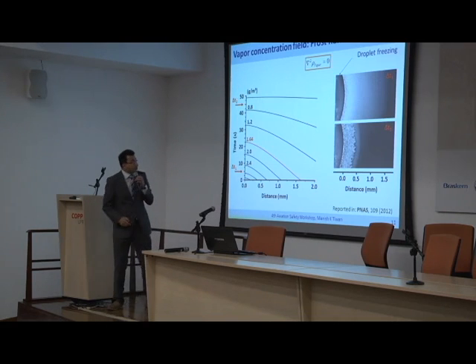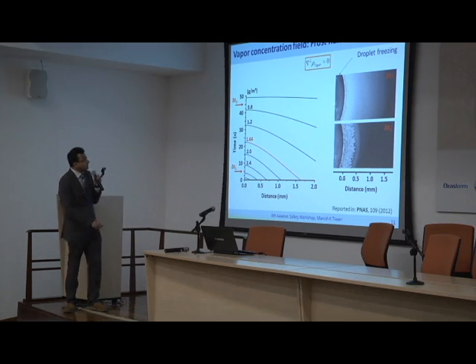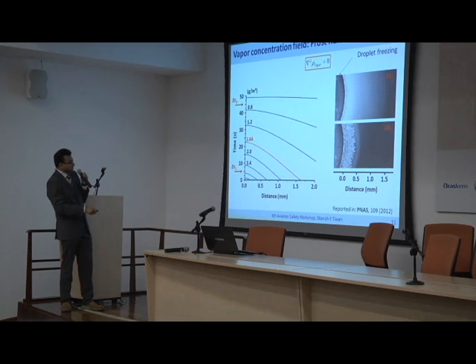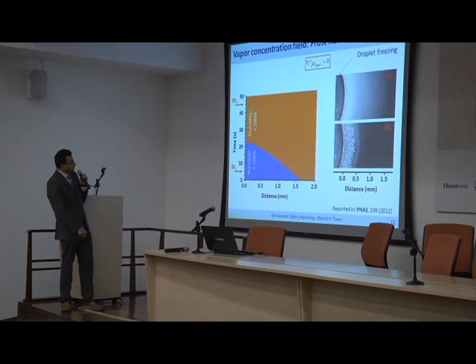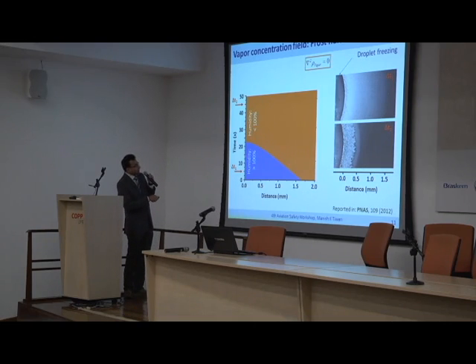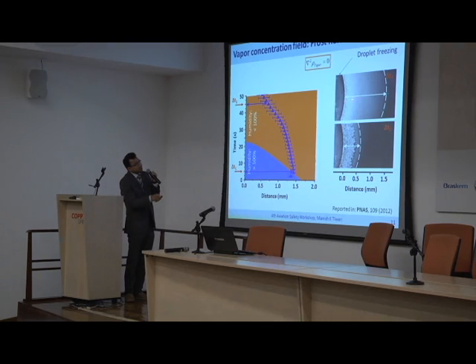So what did we do about that? Well, the first thing I'd like to do is to show you that this indeed is true, because this seems like a lot of hand-waving argument, right? So what I did is I solved a vapor diffusion equation around my droplet, and if you do it with respect to distance and time around, let's say, this original drop, you can actually very simply come up with a humidity envelope, which shows that around your original droplet, there are going to be regions which are going to be greater than 100% in humidity, very close to it, but there are those regions. And away from it, there are going to be regions which are going to approach my environment, which is at lower humidity. This is the extent of the so-called condensate ring, which is forming out of this original droplet.